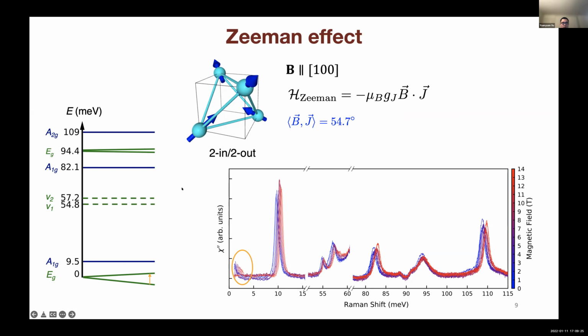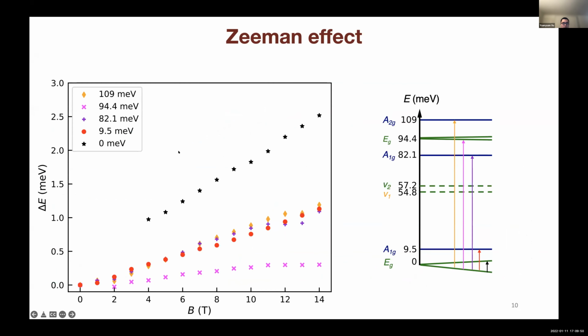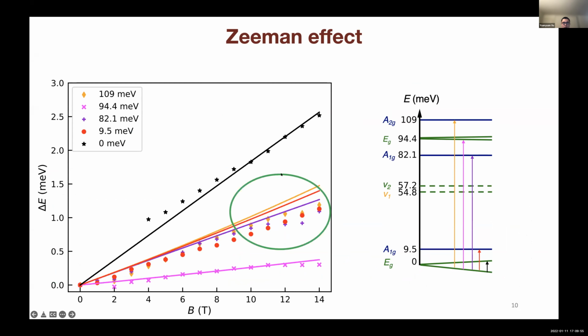Generally, we observed all the transitions from the lowest energy state to all of the higher energy states. And the splitting of the ground state gives a trend of hardening to all of these peaks. Remarkably, this small peak is the transition within the splitting of the ground state doublet. And here I extract the energy shift of each peak, and the solid lines are the calculated results based only on the single ion physics.